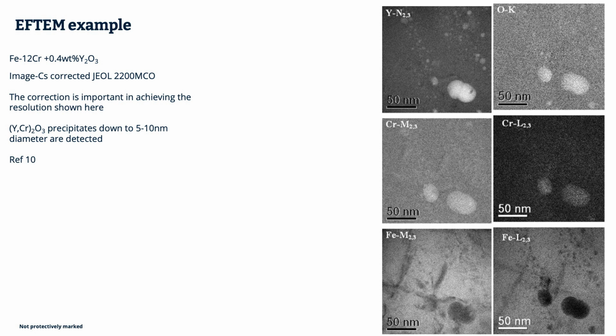And in this case, they'd chosen quite a low energy loss for the yttrium edge, which wouldn't normally be used, but by using some good data fitting techniques, they were able to unscramble the presence of the nearby plasmon energy and produce some really impressive images for yttrium there. In other systems, yttrium can be quite difficult because it overlaps with other elements, so that's why this particular paper was on my radar.